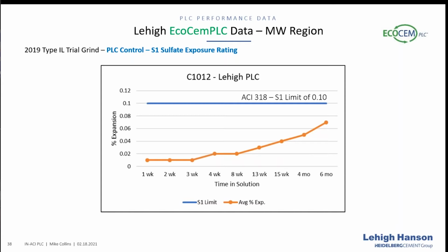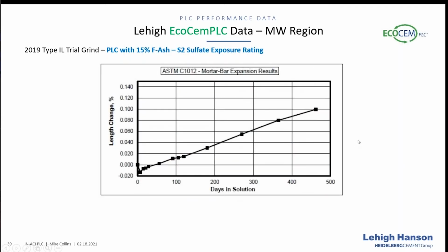Because the clinker chemistry is the same, and Lehigh is a Type 1-2, typically without an SCM. Lehigh Type 1-2 cement meets the S1 sulfate exposure rating on its own, and we see that carry over to the PLC using that same clinker. So the PLC control reaches S1 just fine. When that Lehigh PLC is used with 15% F-ash, it easily met the S2 sulfate exposure rating.